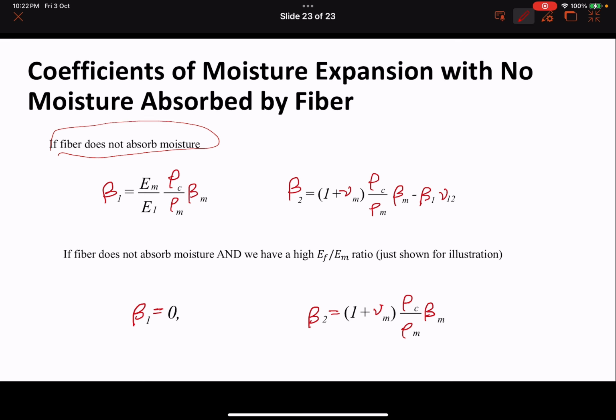And then beta 2 again reduces to a simpler formula. And then if we say, okay, we use a high EF to EM ratio, meaning the fiber is very, very stiff compared to the matrix, so the matrix is a very weak material, then this ratio is almost 0. So then beta 1 becomes 0. If you apply that to beta 2, you're left with a very small number. Okay, so you need not memorize any of this. Of course, all your quizzes are open book quizzes, but this is a very important part that we have not discussed yet. With that, we are finished.